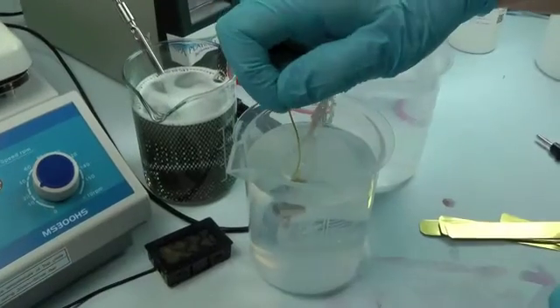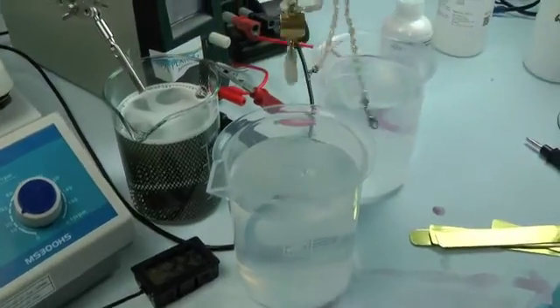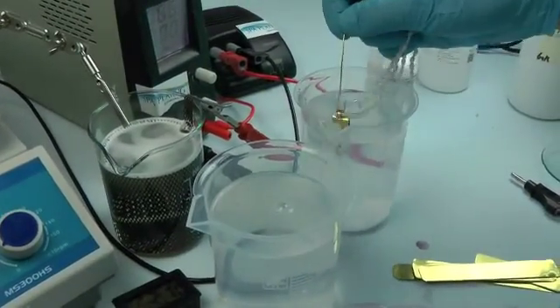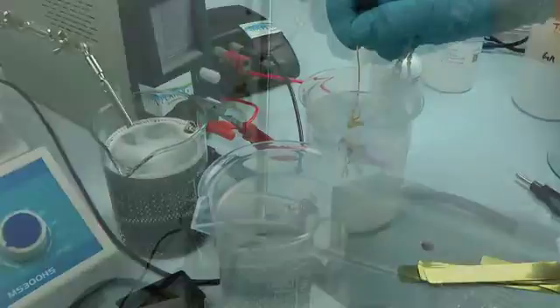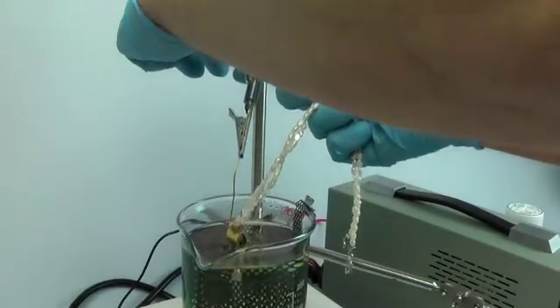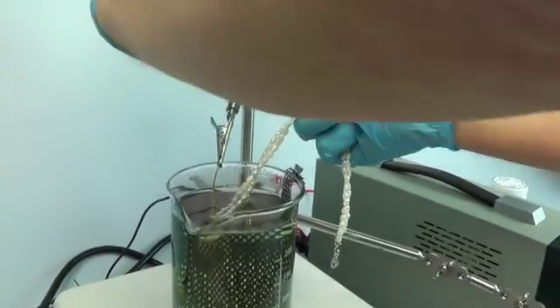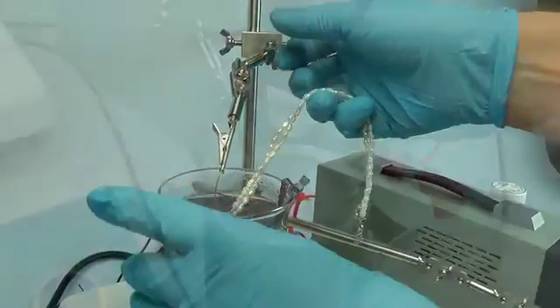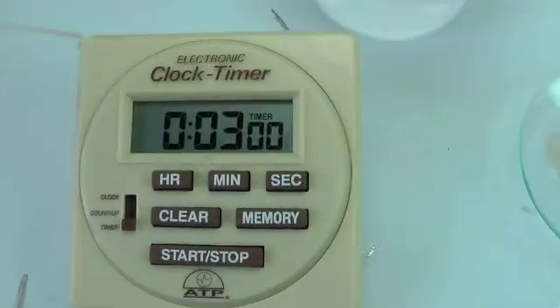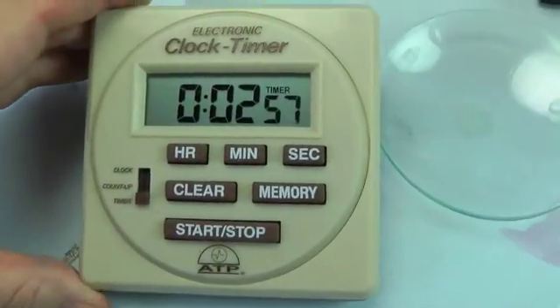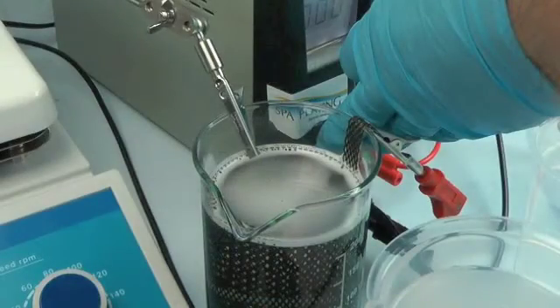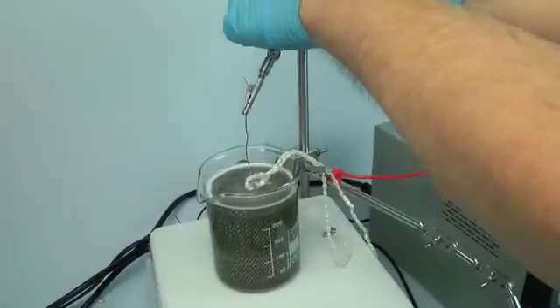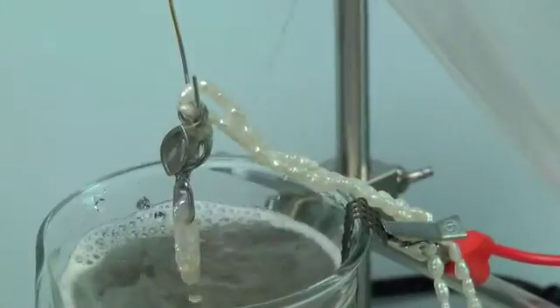Once cleaned, rinse in the two rinse beakers and fix it to the gold-plated jigging wire above the palladium plating tank. Lower your work into the tank and switch on the tank plating rectifier. Set the plating timer to the right time, and once the time's up, switch off the tank plating rectifier, remove your work from the plating beaker, and pass it through the two rinse beakers.